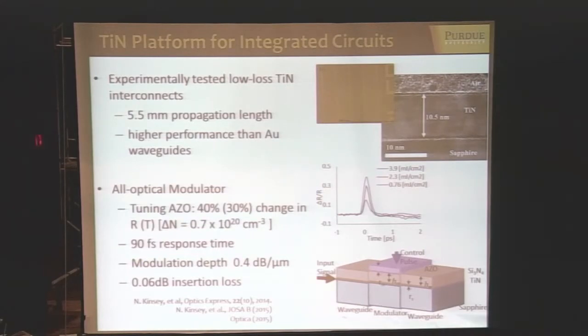The response time is extremely short, 90 femtoseconds, basically meaning it could work in the range of 10 to 100 terahertz speed. It's a very fast modulator. Modulation depth is very respectable, 0.4 dB per micron, and insertion loss is very low.